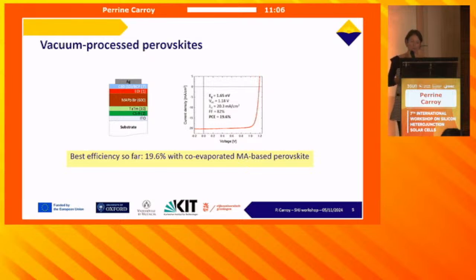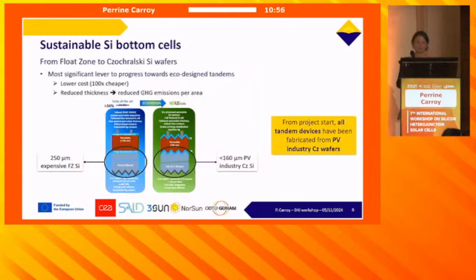And also a 1.65 eV band gap, which is probably close to a world record for this kind of band gap for vacuum processed perovskites. Then we want to make sustainable tandems on sustainable silicon bottom cells.